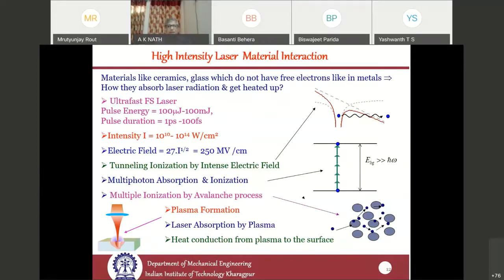So there comes the effect of high power. When you have very high power lasers which can generate power density on the surface in the range of 10 to the power 10 to 10 to the power 14 watts per centimeter square, correspondingly the electric field of this electromagnetic wave will be very high, in the range of around 250 megavolts per centimeter. Under these conditions, because of tunneling ionization effect under the intense electric field, some of the bound electrons are going to get ionized and become free. There is another mechanism that happens when you have got very high laser power densities of this order.